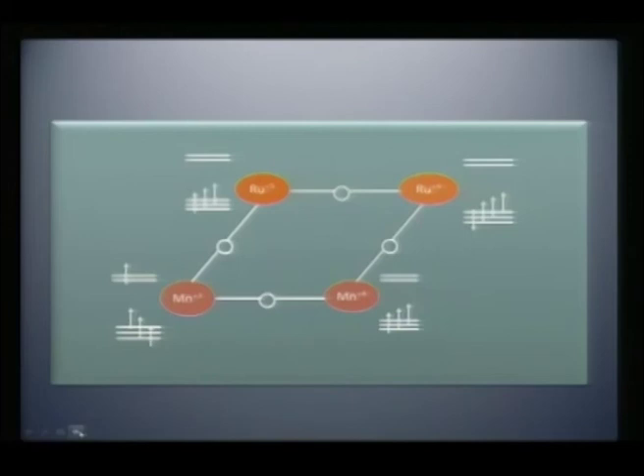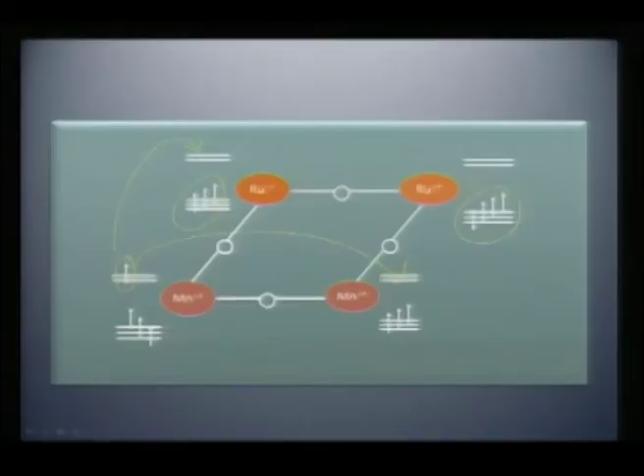So, we can sum up with a new double exchange model where we say that the Mn3 plus eg electron now has both ruthenium 4 plus and ruthenium 5 plus, and as a result this eg electron either can go here or this eg electron can go to this empty orbital. Therefore, you have two double exchange pathways where you can drive this compound metallic and ferromagnetic because you are providing a similar state. In other words, this Mn4 plus is isoelectronic and has iso-orbitals like ruthenium, which makes this a more important compound to study.